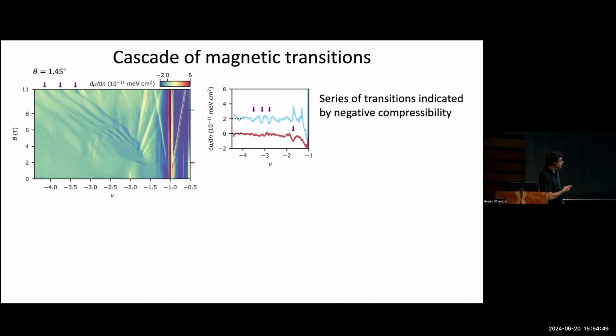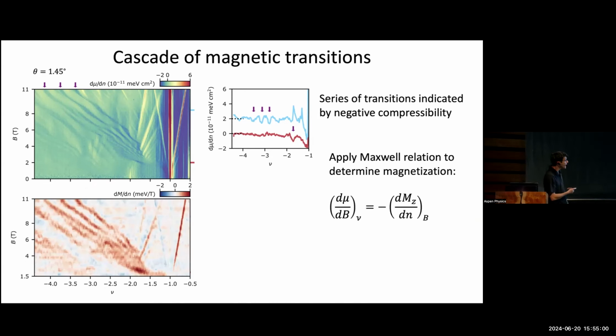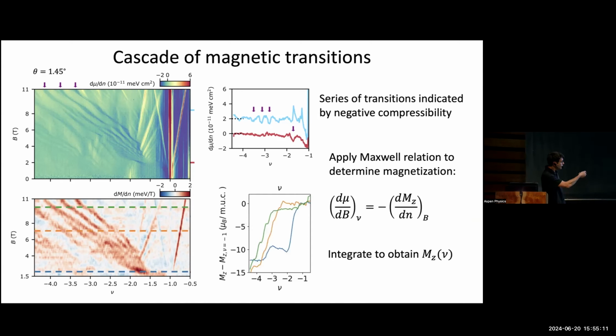But on the other hand, back quickly, you actually look at the same sorts of blue transitions. So this is now a different twist angle. You can see there's a series of these blue streaks. We can use a Maxwell relation to go from the measured compressibility to the magnetization, and its change as a function of carrier density as we dope the system. And just by integrating along these particular lines, you can then understand how the magnetization changes. And we see that there are these abrupt drops as you go through these features here. So these are really magnetic phase transitions. We can say that with certainty based on our data and the Maxwell relation.